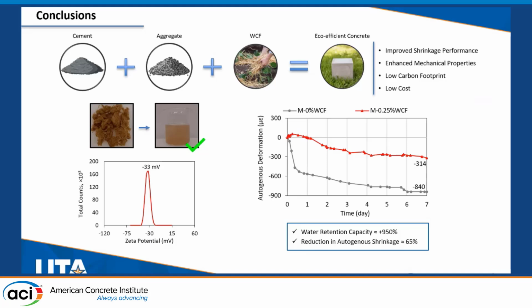In conclusion, using waste cellulose fibers, I produced eco-efficient composites with enhanced mechanical and shrinkage performance and lower carbon footprint and cost of composite production. According to our results, a monomodal distribution of zeta potential values was observed that resulted in a suspension with improved stability. Also, because of the high water retention capacity of the fibers that could mitigate the internal stresses caused by the self-desiccation mechanism, significant reductions in the autogenous shrinkage values of up to 65% were observed.